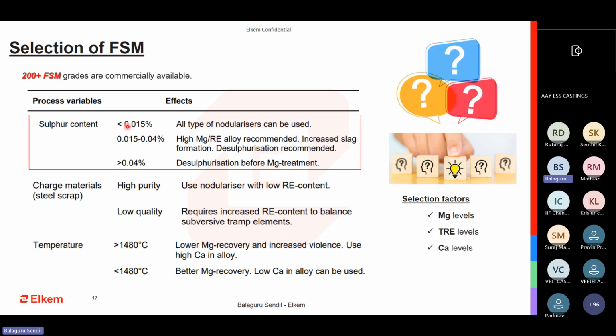If your sulfur content is less than 0.015, you have to go for a lower magnesium FSM, 7, 6, 5 percent. If your sulfur is on the higher side, then you can go for an 8 or 9% grade. The 8 and above percentage of FSM should only be used when you do not have good sulfur control. Sometimes you might end up getting 0.018, 0.020 in your charge mix. Then you can go for higher magnesium FSM.